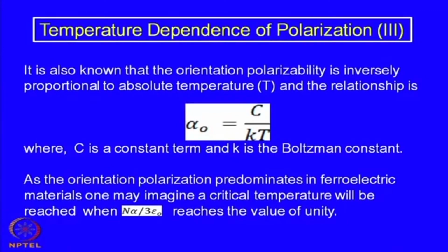It is also known that the orientation polarizability alpha is inversely proportional to the absolute temperature. The temperature dependence of the overall polarization comes from this particular equation.